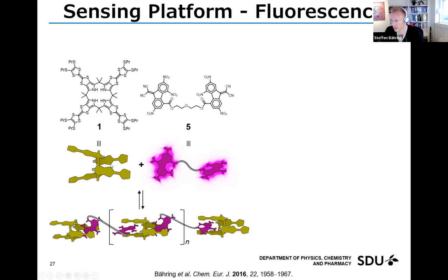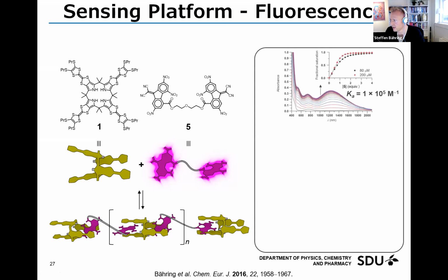So you can see here that mixing these two together, we were expecting to form some type of supramolecular polymer or oligomer, depending on the binding constants. And simple absorption spectroscopy showed that at different concentrations, we're able to get a strong binding. So this is an overall binding of 10 to the 5th.